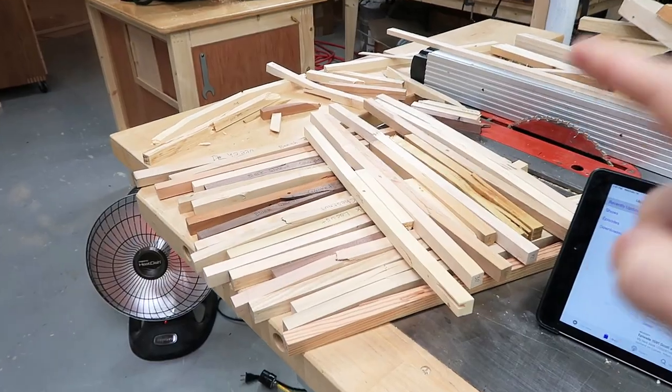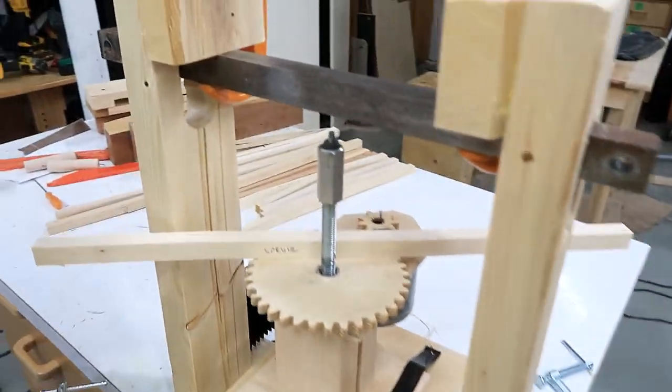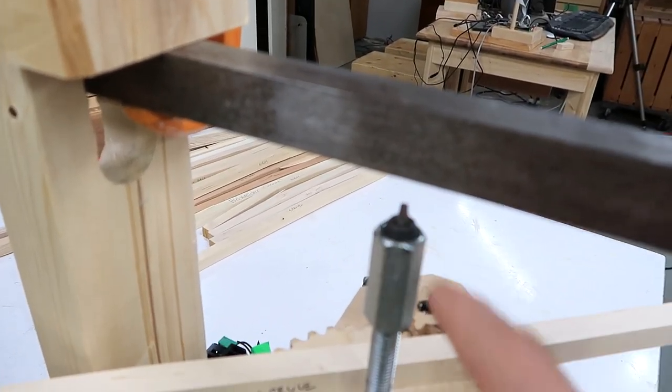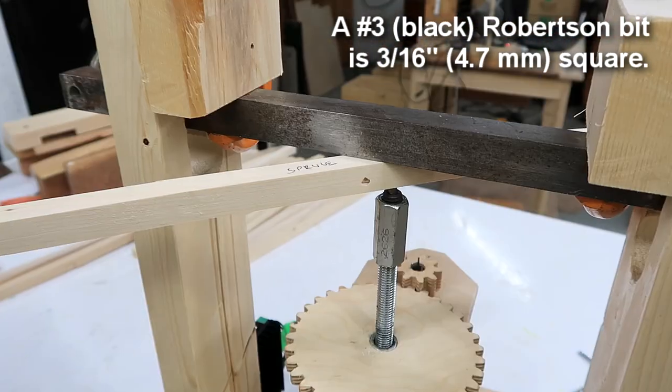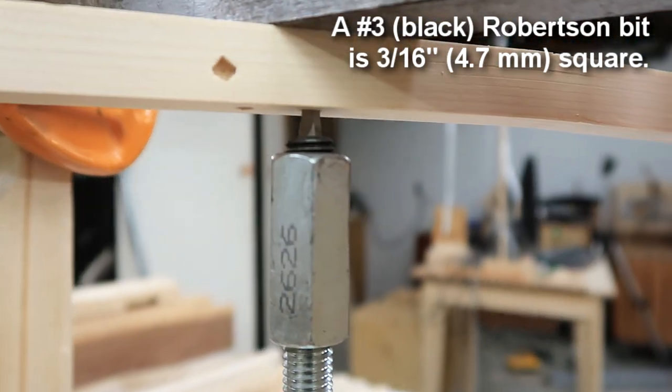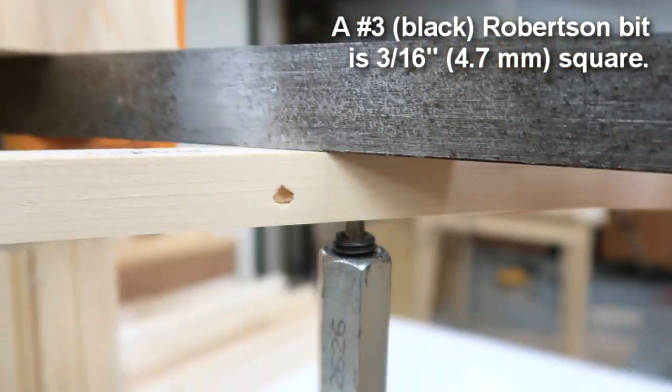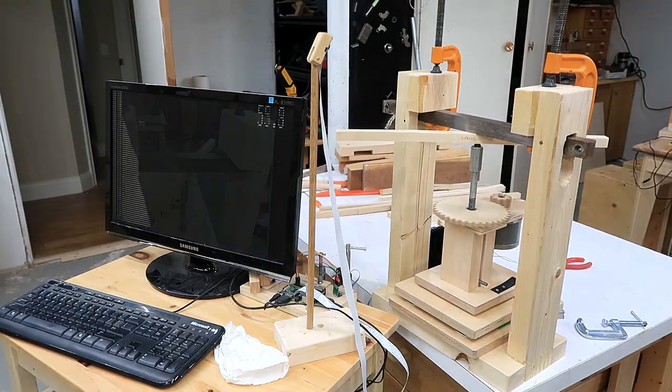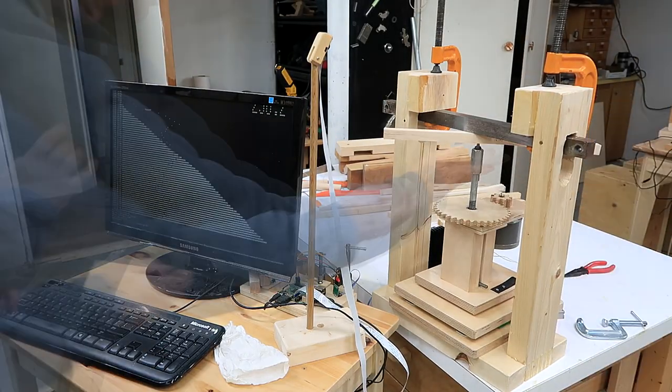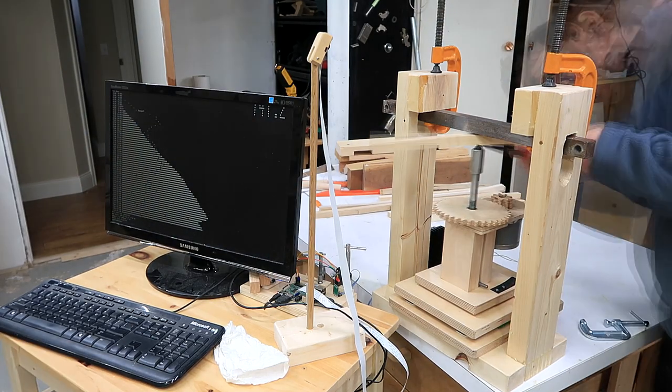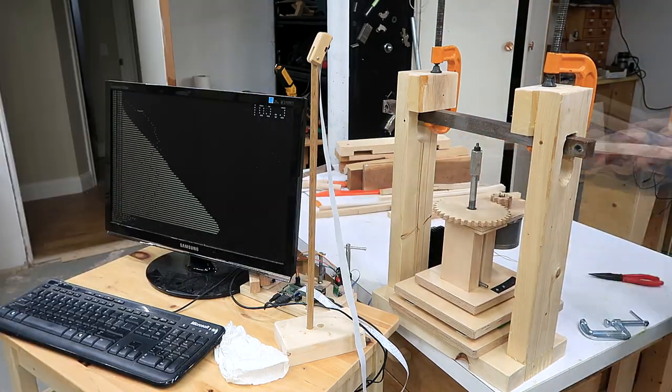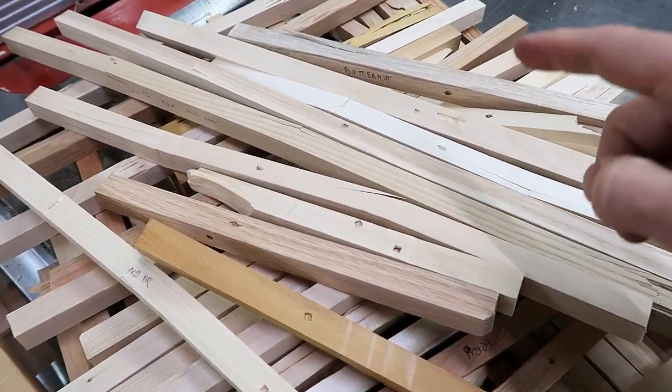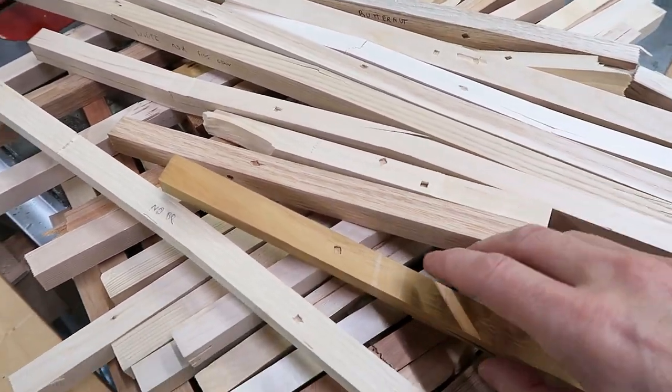I'm now testing all these broken bits for hardness by pushing a number three, I think that's the black colored Robertson screwdriver bit. So it's just pushing it five millimeters into the wood and measuring how much force that took. I'm not compensating for flex in the machine, but the whole thing is a relative measure anyways. The machine isn't strong enough to do a proper Janka hardness test. So now I have over 100 divots pushed into all my test pieces.